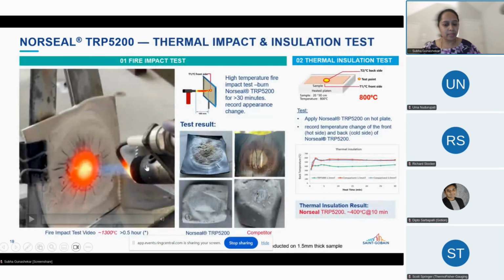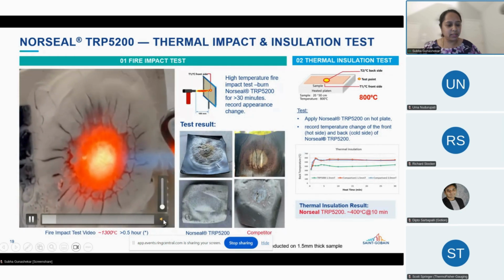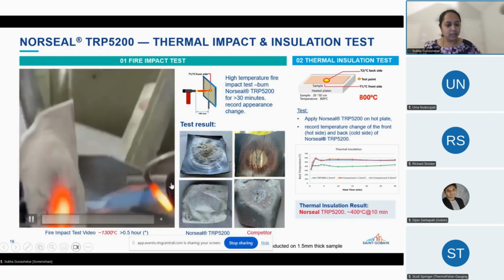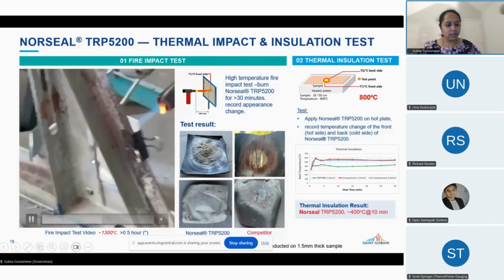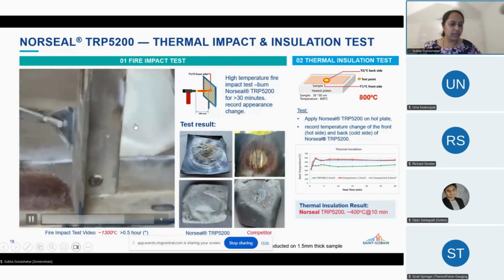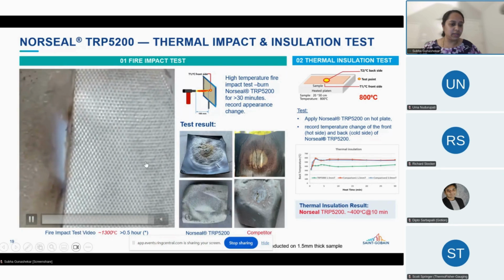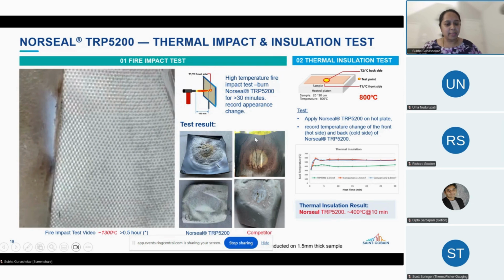So this is an example of the flame testing that was done on this material. Torch of 1300 degrees Celsius for about half an hour. You can see in the backside there is nothing. There is no damage to the product and no propagation. It's fairly intact. Whereas this is a competitor product, you could see it burned through and had more scratches. And in terms of the temperature insulation properties, it was much higher compared to this particular product, which we tested here. At 1.5 millimeters, the backside or the cold side temperature was about 400 degrees Celsius. Whereas an alternate, one of them is mica, just a sheet of mica, and the other one is a similar product from a competitor. The backside temperature was about 500 degrees or close to 600 degrees Celsius here.